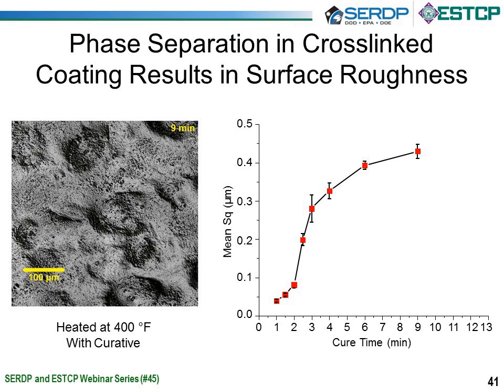Overall, we're overcoming the thermal process of deprotecting the isocyanate, the pressures that are involved in the cross-linking or expansion and contraction of the polymer, gravity, and any other bulging effects that are resulting in the domain formation. Eventually, we realized that the greater viscosity is resulting from a higher cross-link system, and therefore the individual monomers or polyols are less likely to be able to move to form a smooth surface, as is observed in slide 42.